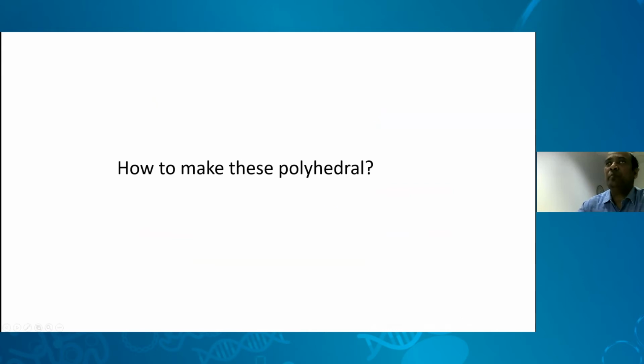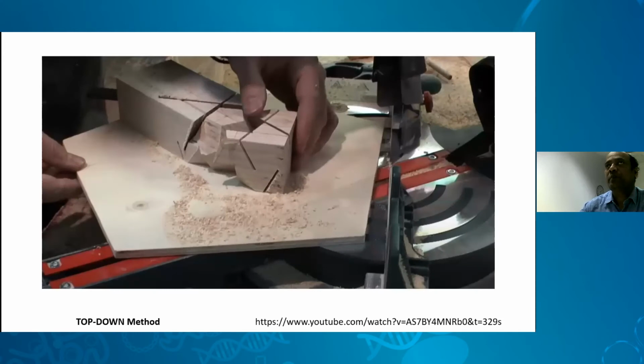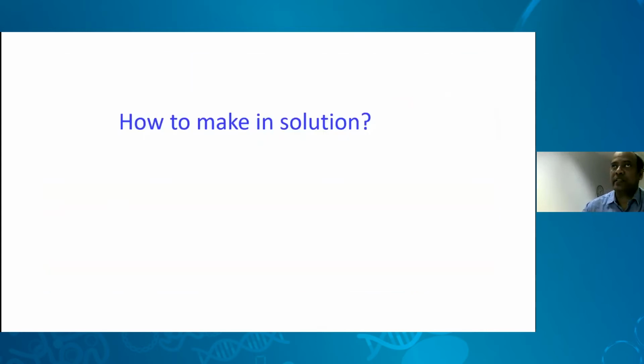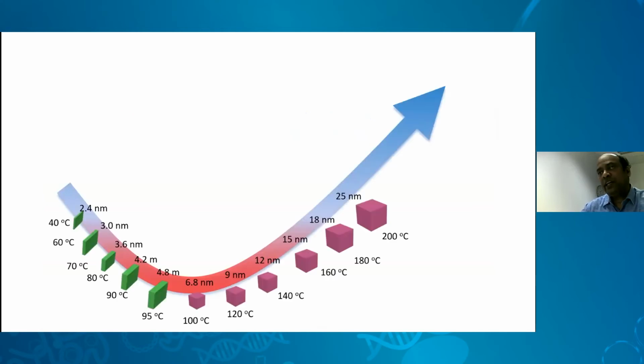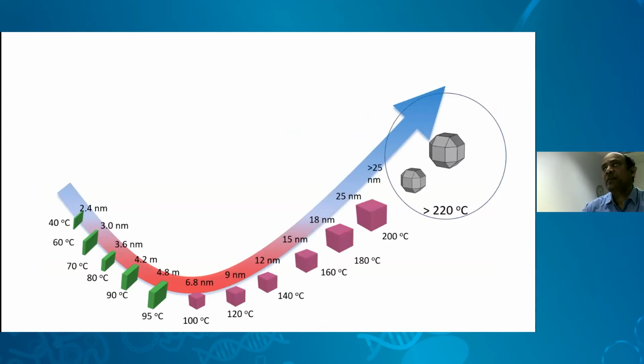So now what happens, how do we make these polyhedra? When we try to understand this, if we go for cutting down in the physics way, called the top-down method, one can cut a piece of wood into a rectangle or a cube and get these polyhedra. But how do we make them in solution, in the bottom-up approach? You have to start with the atoms, mixing the atoms, and a particular facet has to be stabilized. While carrying out this particular reaction that I was showing, after 200 degrees, we continued to inject. Very surprisingly, we found these are no more cubes. There are some new facets coming out of particular materials.